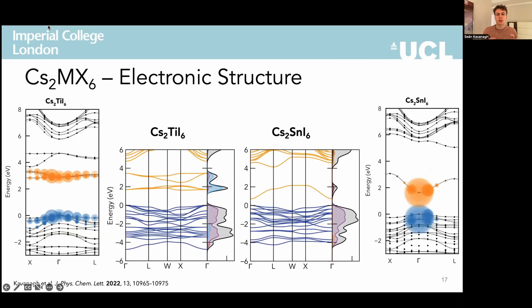These results reveal qualitatively different electronic structure between the tin and titanium compounds, where strong structural and electronic localisation in the titanium analogues results in significant exciton binding dominating the low energy absorption range. For the tin iodide compounds, the dispersed Sn conduction band avoids these effects with weak Wannier-Mott exciton behaviour. These qualitative differences arise despite the same crystal structure and cation valence, with only the frontier orbital character differing, demonstrating the crucial importance of accounting for chemical effects when employing ionic substitution within materials design strategies.